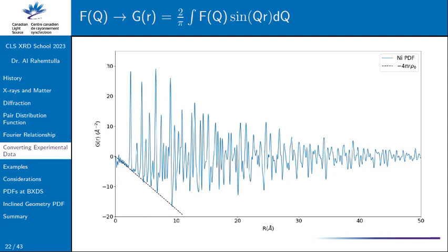You can, but it's something I don't recommend. These ripples here are the evidence of that finite boundary. You can add an artificial damp function to smooth it out so it goes to 0. But what you're doing is adding an artificial damp. If you remember, as I played around with that damp, the peak got broader and broader. That's what you're doing to your real data: convoluting it, making it broader, for the purpose of getting rid of termination ripples. So you're basically killing some of your results to remove artifacts.